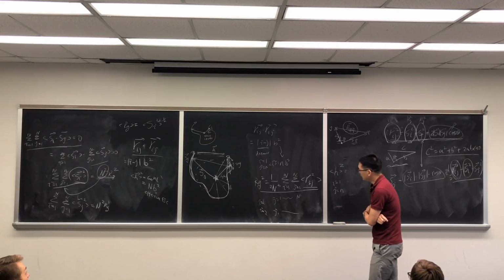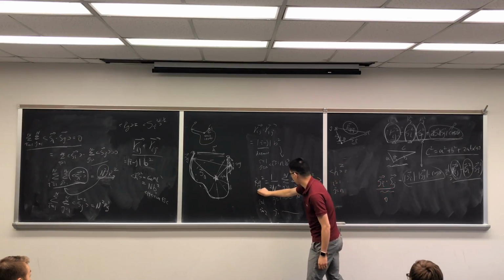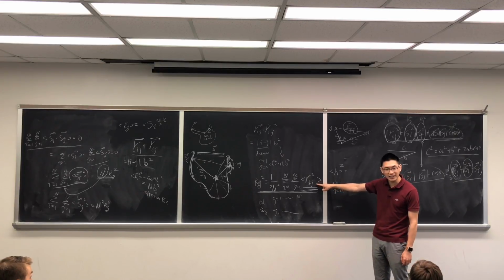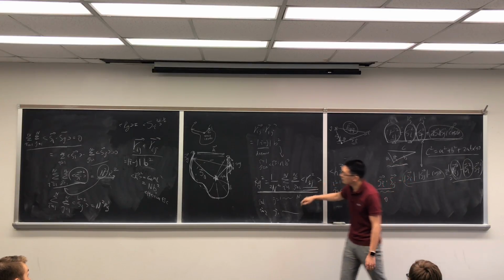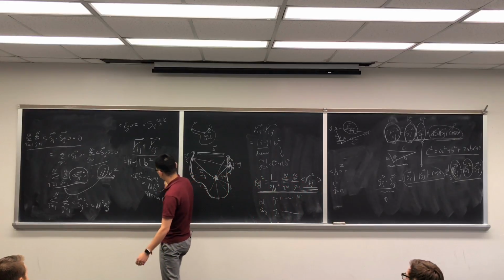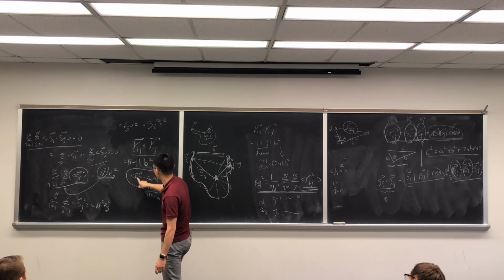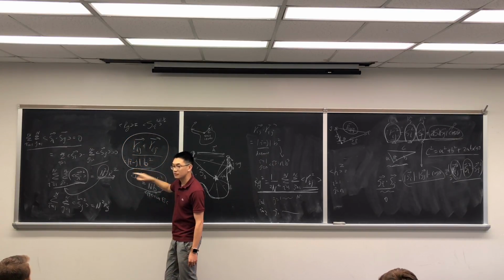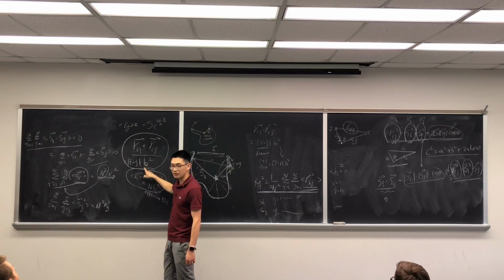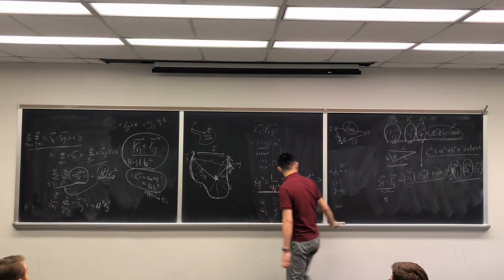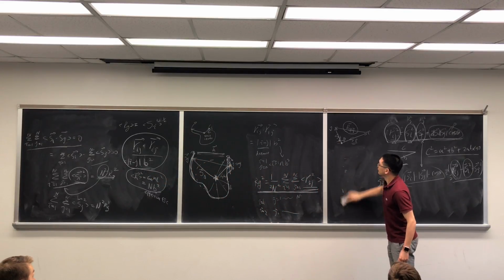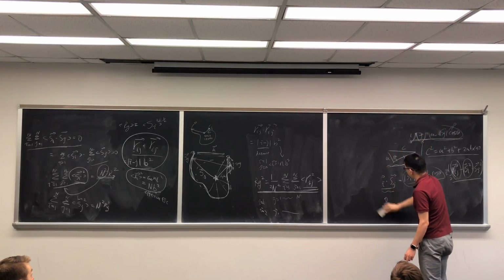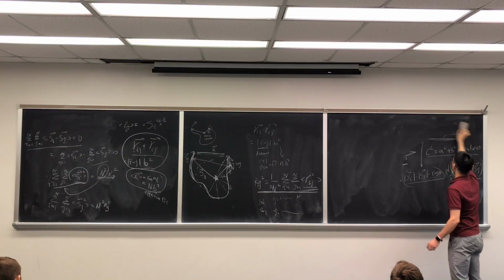Okay, so if we know this, the rest is relatively straightforward for us to figure out, because Rij is very easy to calculate. We discussed it here. Rij would be this value: the sum from i to j of b squared. So let's give it a little bit of a kick, finish this definition, then we can go to a few examples.